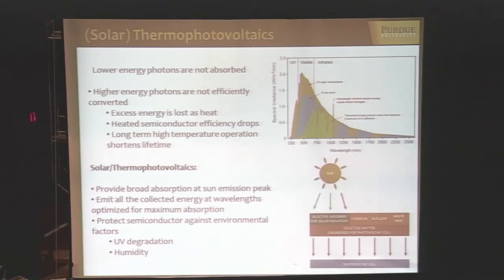They are not used really. And if the energy of the photon is much higher than the gap, then the efficiency of conversion is not that high. So as a result, what you could buy now is something in the range of 20%, with the theoretical limit around 30%.